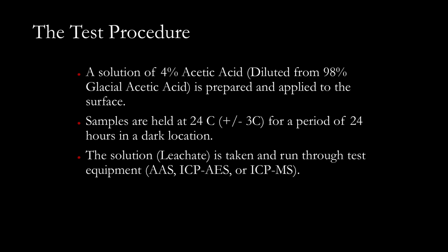The test procedure that we use is very important. This is to simulate a worst case scenario. This is the maximum amount of material we can leach out of a given glaze. How it's done is we prepare a solution of 4% acetic acid, more commonly known as household vinegar, diluted down from pure glacial acetic acid to a controllable level.